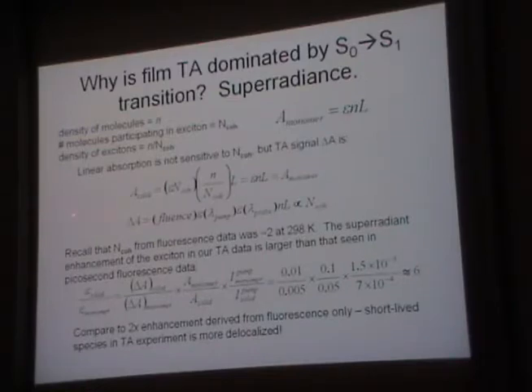So we see a larger delta A signal in the solids, and that's because we have basically larger effective epsilons in the solids. And you can do a ratio of the epsilon that you get from the solid, from the monomer, that you can sort of extract by knowing your fluence and everything. So we know the fluences, and we know the linear absorption of the samples. We measure the delta A, so you can do that ratio. And you find out that the effective epsilon of the solid is 6 times, roughly, let's take 6 plus or minus 1 at least, that of the monomer. Okay, so we do have a superradiant enhancement.